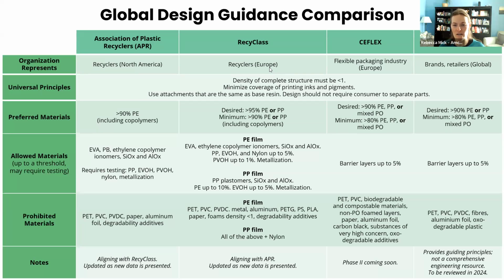I think you can see that there are some best practices that no matter what region you're designing for, you can pretty comfortably follow these guidelines and be able to have some harmonization across your packaging structures. So first and foremost, all of these are really focused on polyolefins, or, as I mentioned, in APR's case, PE. And that means that in order to get through the system correctly, we need to make sure that the density of the structure is less than 1, right? In many cases, they have to go through some kind of sink float. So we want to make sure that we're keeping our structures less than 1.